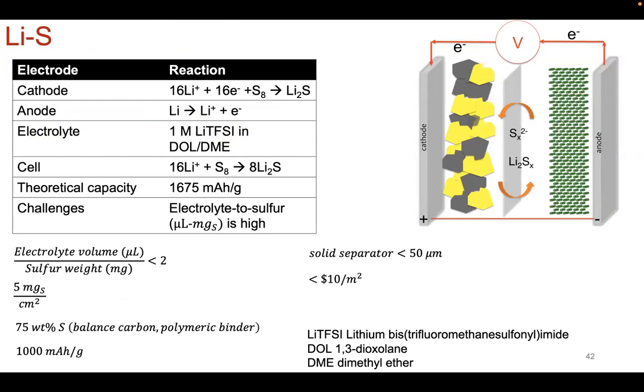Now, the chemistry that we'll be talking about is quite different for lithium sulfur batteries versus the lithium ion batteries that we talked about, right? So in terms of the number of moles of lithium ions that can be transported, you can already see here that it's quite a lot. It's more than, let's say, 0.5 molar equivalent for lithium cobalt oxide for the intercalation-based mechanism. So the conversion-based mechanism does offer transport of more molar equivalents of lithium ions, which increases the energy density. But the electrolytes are also quite different. From what we've talked about previously, typically 1.2 molar LiPF6 in carbonate-based solvents. Now we're talking about ether-based solvents.